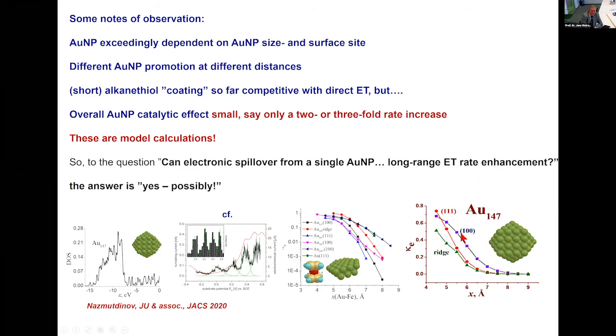You can also see it depends on the distance. At some distances, the catalytic effect is larger than at other distances. We also studied the effect of short alkanethiol coating, and we found this is competitive, but this is work which is going on. This is unfinished work at the moment.